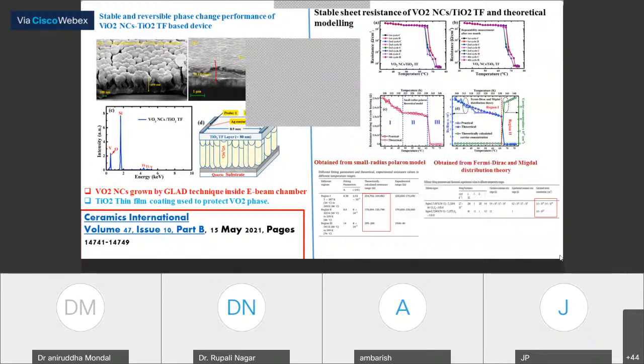We have seen a clear change of phase from semiconducting to metal at nearly 60 degrees, and this change is also stable after 1 or 2 months. And we have used some theoretical approach to calculate different characteristics of these materials, and we have seen these materials are very much applicable. We have obtained the small polaron model to find out the resistance in the semiconducting and the metallic phase. And we have also newly determined the electron concentrations of the materials in the semiconducting phase and the metallic phase, which is the uniqueness of the theoretical model that we have determined here.